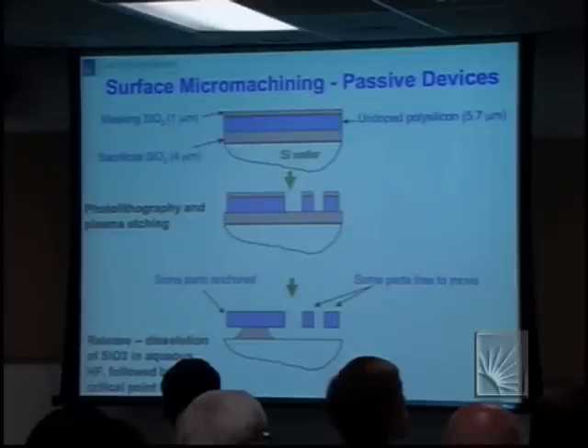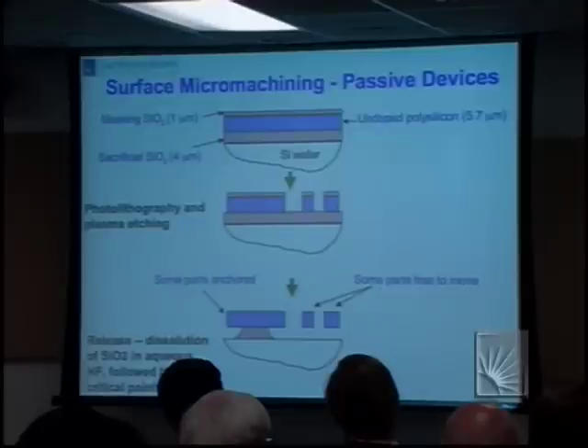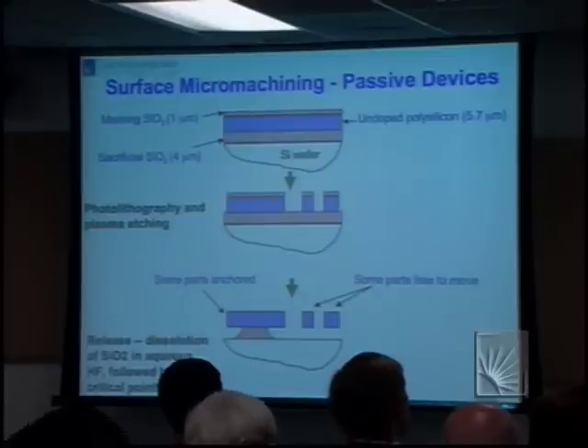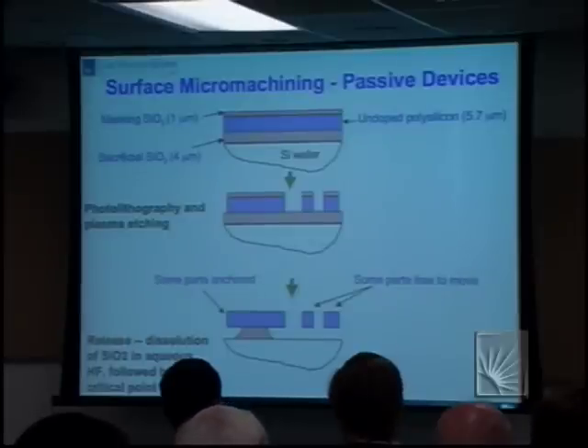Our devices have all been very simple, so-called single mask devices. We take a silicon wafer, we oxidize it, thermal oxidation to make a sacrificial oxide. Then this is the working bits of the unit. It's, in this case, LPCVD of polysilicon. I'll tell you more about that in a moment. And then we put down about a micron of CVD silicon oxide, plasma enhanced CVD now, and use this as a masking oxide. And we have conventional photolithography and plasma etching, both for the SiO2 and the silicon.